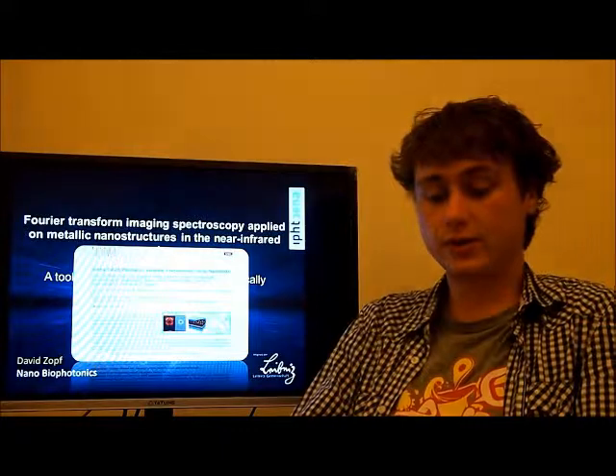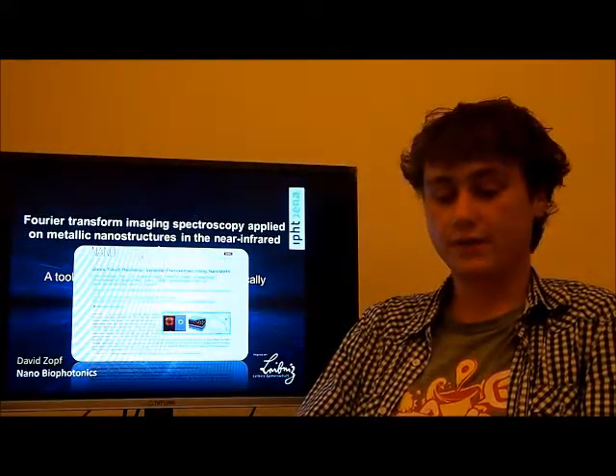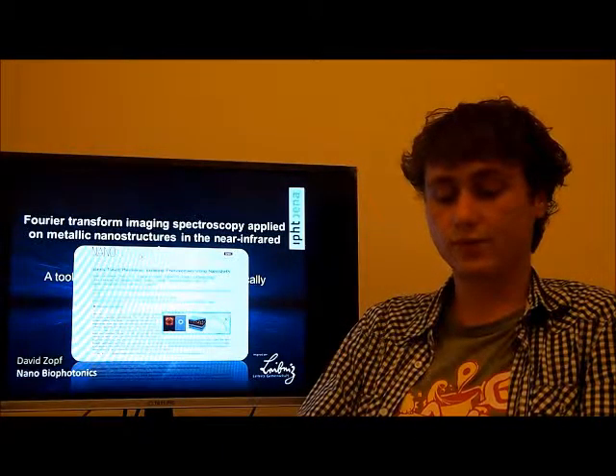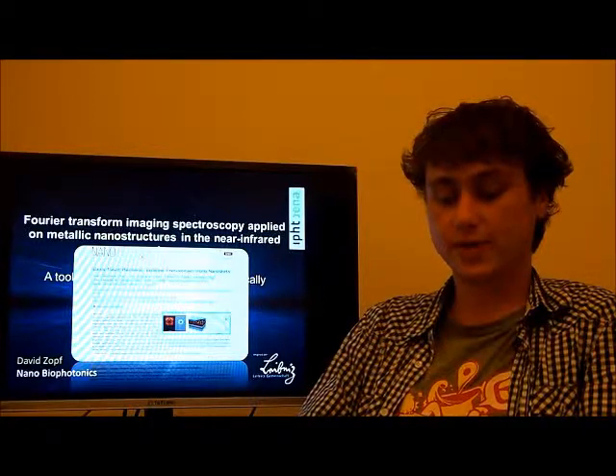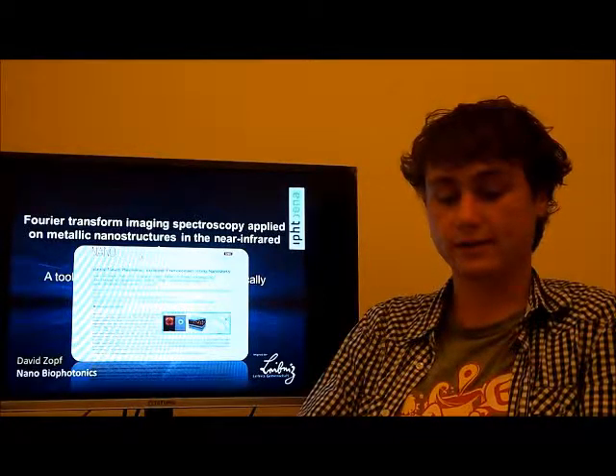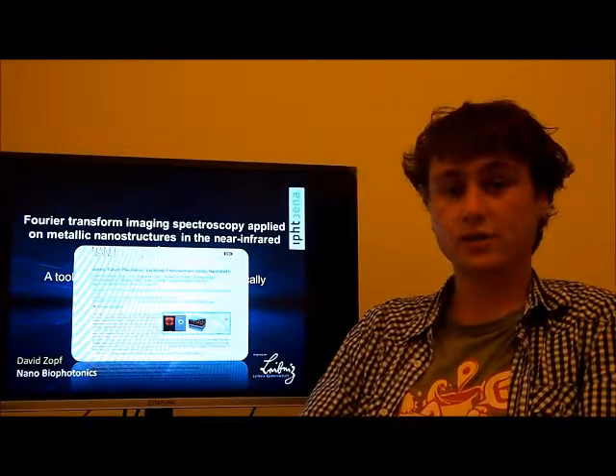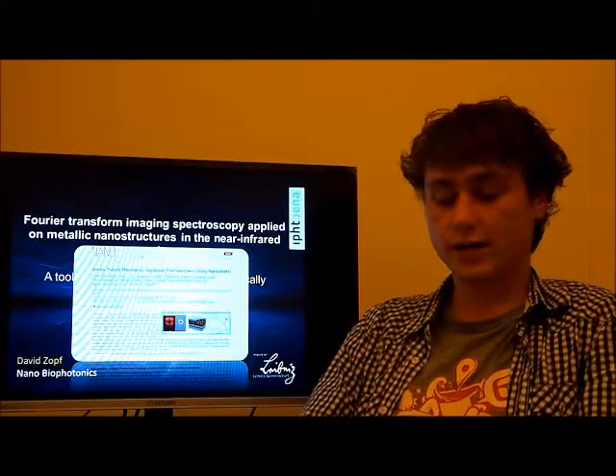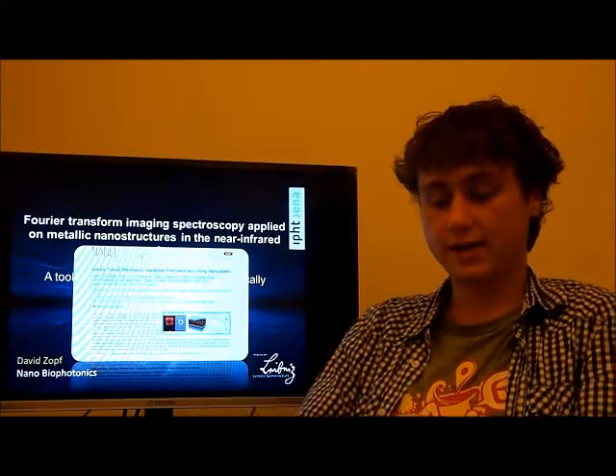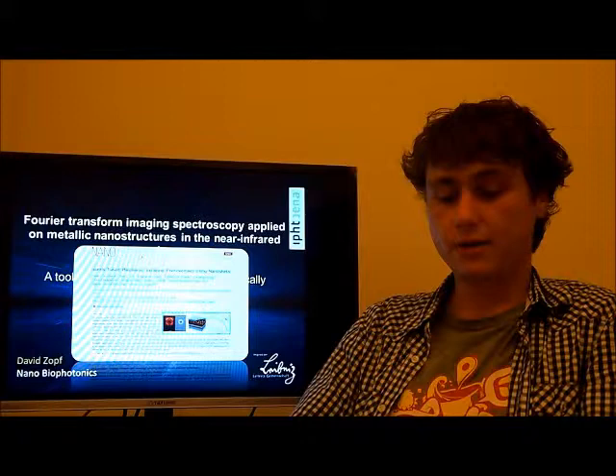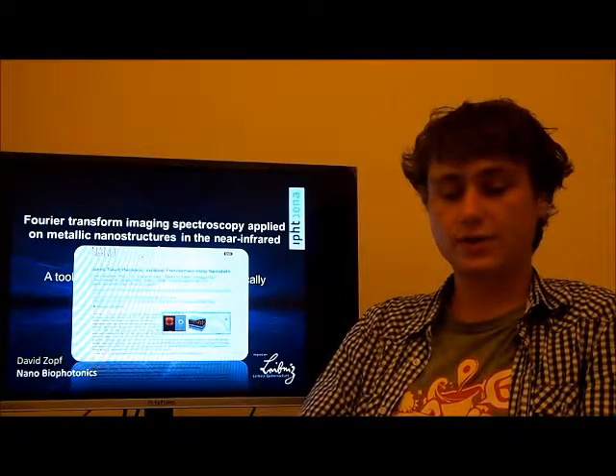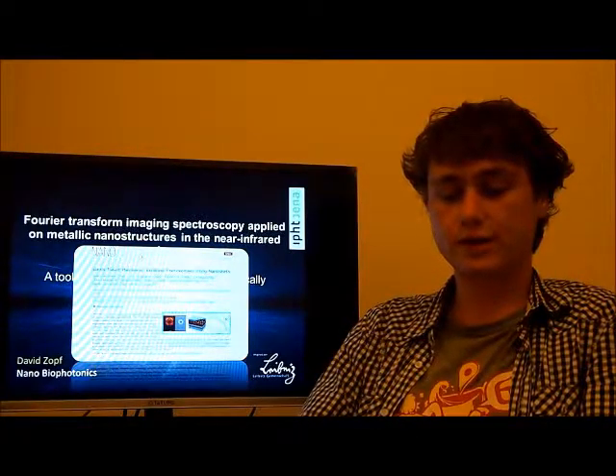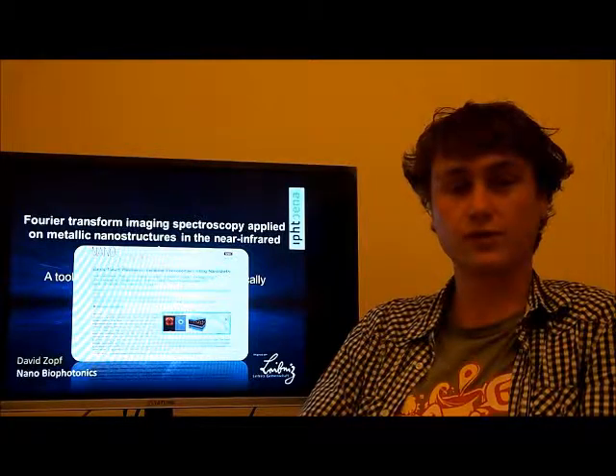Edward Sargent's group from Toronto University reported a 35% enhancement in the photocurrent in the near-infrared spectral region using nanoshells. These nanoshells consist of a thin gold shell and a silica core. The evaluation of the quality of these structures is a crucial factor to optimize the performance of future solar cells.